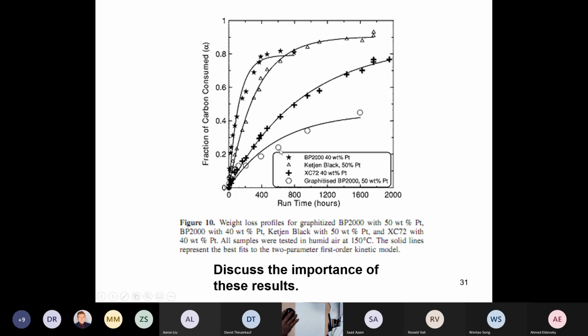So what we did was we took Black Pearls 2000. You can see the weight change versus time for Black Pearls 2000 at 150 degrees C and humid air. And we took the Black Pearls 2000 and graphitized it. So we heated it up to about 2200 degrees C. And then we had the catalyst supplier put 50 weight % platinum on it. And you can see that the corrosion rate slowed down enormously compared to the non-graphitized material.